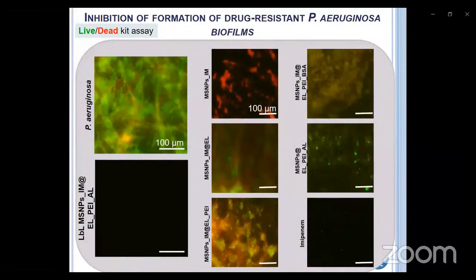So the cell viability within the biofilm structures was studied using live dead kit assay, as we can see on the microscopic image. And the bacteria form well-established biofilm. The drug-coated mesoporous silica nanoparticles showed bacterial killing properties. No bacterial inhibition activity was observed in the other controls. The antibiotic solution in the layer-by-layer mesoporous silica nanoparticles with alginate layers as upper layer impeded the biofilm formation.